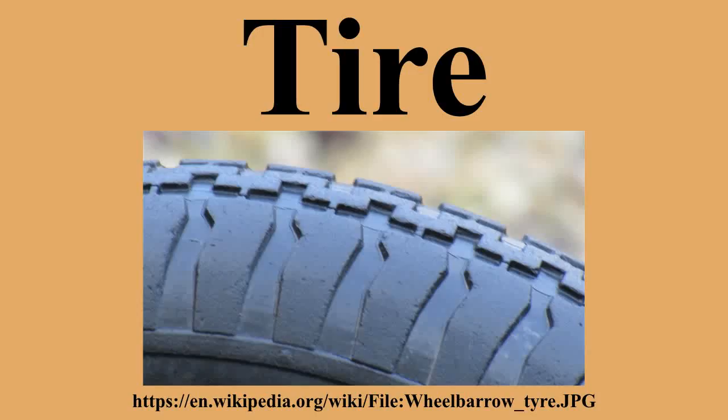Sipe. Tread lugs often feature small narrow voids, or sipes, that improve the flexibility of the lug to deform as it traverses the footprint area. This reduces shear stress in the lug and reduces heat buildup. Testing of identical siped and unsiped tires showed measurable improvements in snow traction and ice braking performance. However, it also showed diminished performance, extending braking distances on wet and dry pavement by a few feet on siped tires.